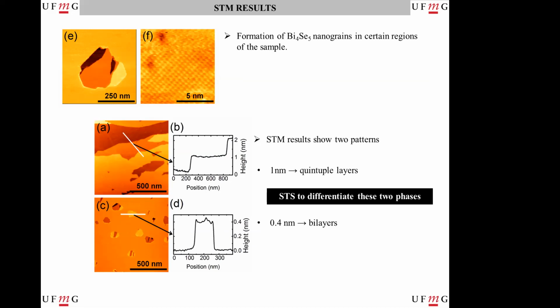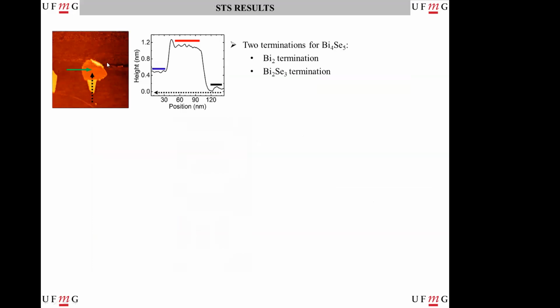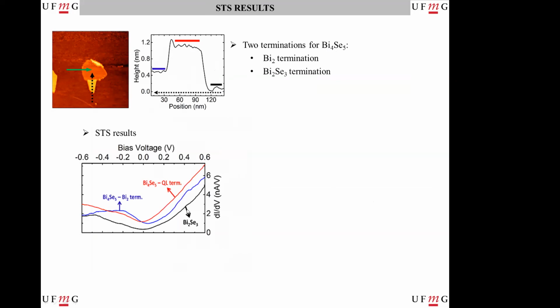So then we use STS, scanning tunneling spectroscopy, to differentiate between these two phases. We took a grain here, like the other ones, and this grain is good because we have three types of terminations. We have a termination of Bi2Se3, and we have Bi4Se5 with two different terminations, one termination with a bilayer of bismuth and one termination with a quintuple layer. The result is here. We have what we expected for the Dirac cone on bismuth selenide, here in black.